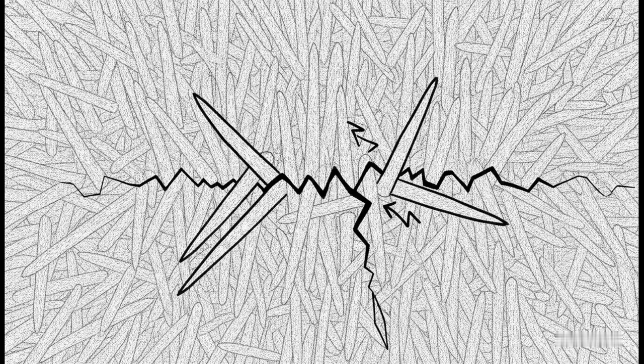Think of these acting like microscopic rebar inside concrete. When a crack tries to form and propagate through the ceramic, these elongated grains physically block it. They cause what we call crack deflection, forcing the fracture to actually change direction and lose its energy, and crack bridging, physically holding the material together. This is the toughening mechanism that gives silicon nitride its almost unheard-of durability for a ceramic.